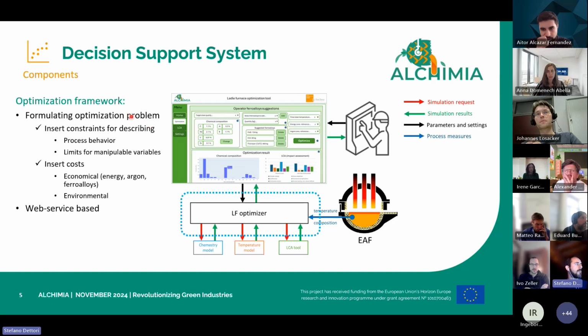Then, thanks to the optimization framework, we can formulate an optimization problem where, for example, we can insert a set of constraints that describes the process behavior, in this case the ladle furnace, but also the limits of all the manipulable variables in terms of, for example, energy usage and the types of operation and so on. And finally, also insert a set of costs that describes the balance, in terms of economic impact, that takes into account the energy consumption, the argon consumption, but also the ferroalloys usage, and also the costs related to